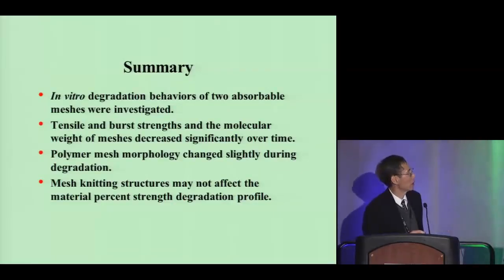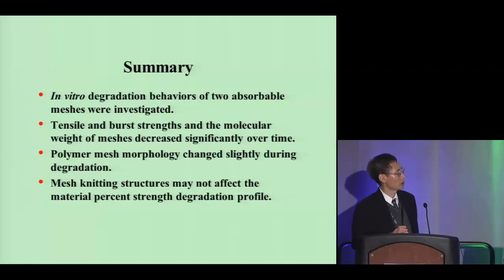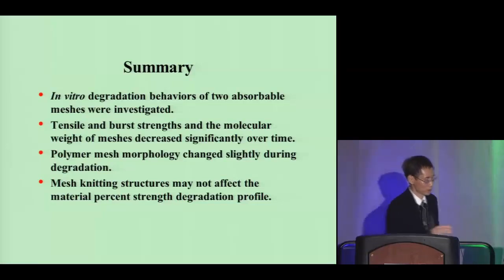In conclusion, we studied the in vitro degradation of two absorbable meshes, and the tensile and burst strength and the molecular weight of the mesh decreased significantly over time. We don't see much change in mesh morphology, whether we use optical microscopy or SEM. There is a close relation between the strength retention and molecular weight. And possibly, mesh knitting structure has a low effect on the material's percentage of tensile strength retention profile.